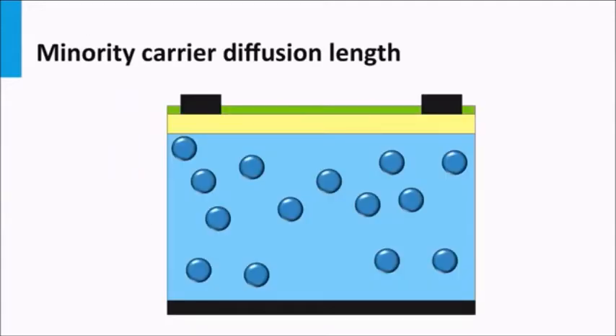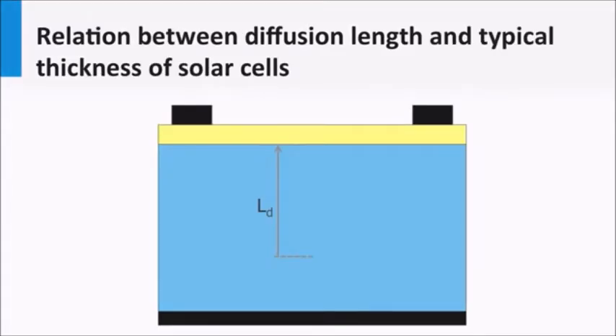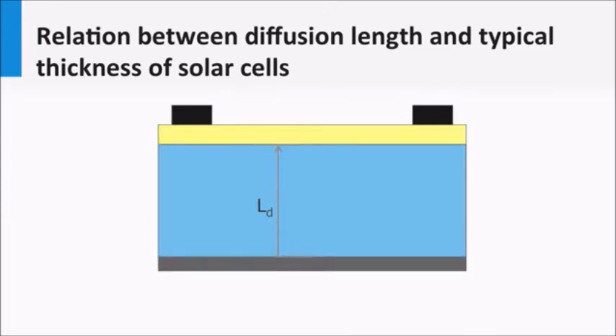This is demonstrated in this simple animation. Let's consider photons that would penetrate far into the absorber layer before they are being absorbed. We want these charge carriers to be separated at the p-n junction or the back contact. But let's assume that these charge carriers are excited at a depth deeper than the typical diffusion length. The excited charge carriers recombine within the typical diffusion length before arriving at the p-n junction. In other words, their lifetime is too short. This means that all charge carriers generated at a depth greater than the diffusion length from the p-n junction cannot be collected. If the charge carriers are generated at a depth shorter than the diffusion length, they can be collected. This means that the diffusion length of the minority charge carrier limits the maximum thickness of the solar cell.